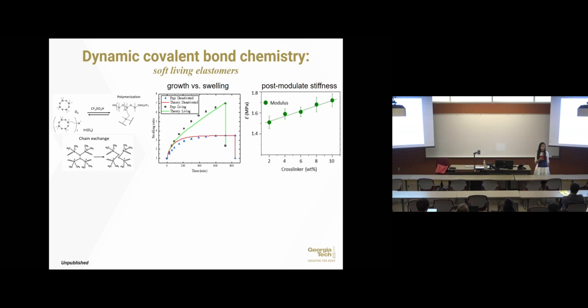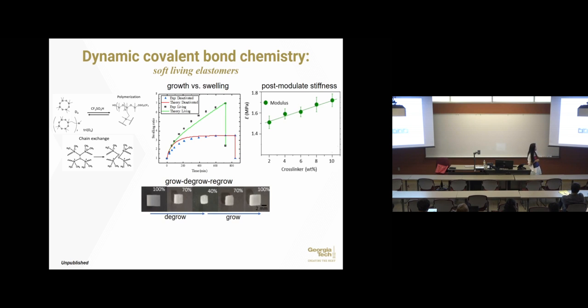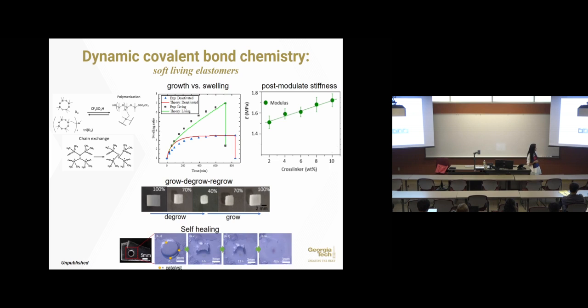And with this monomer and cross linker, as it grows, you can change the ratio. So as it grows, you can grow it to be stronger or weaker. So the Young's modulus can be changed as well. We also showed that this material can grow and degrow, and it's repeatable. One interesting demonstration we did is we punched a hole in it and put a brush of this catalyst here. So this material just grows towards this direction and eventually merges together as one single piece. So this is self-healing we demonstrate, but different from previous demonstrations, it's not that we glue two pieces together. It's really growing to fill the big hole there.